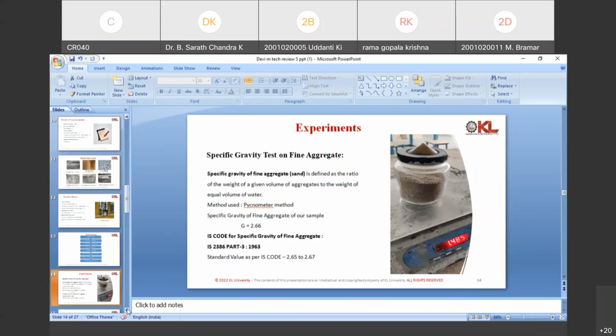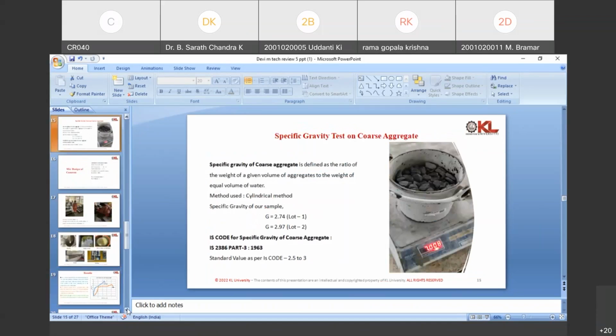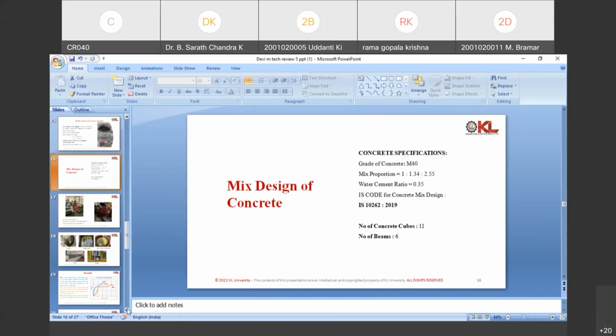These are my experimental work for fine aggregate. Specific gravity test on fine aggregate is defined as the ratio of weight of a given volume of aggregate to the weight of an equal volume of water. Specific gravity of fine aggregate is 2.66, and specific gravity of coarse aggregate is 2.97. Mix design of concrete: grade of concrete is M40. Mix proportion is 1:1.34:2.55. Water cement ratio is 0.35.